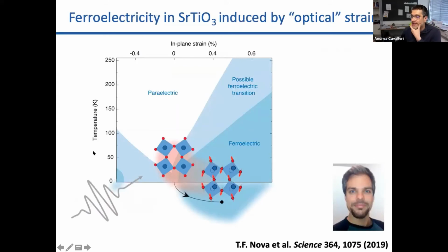This is work done by my student Tobianova, who took the famous failed ferroelectric strontium titanate, which is also known as a quantum paraelectric material, which never acquires ferroelectricity at any temperature, despite coming very close to it, at all thermally accessible states. We have shown that by using light and applying strain in this material, we could induce a ferroelectric state all the way up to room temperature. This was a metastable ferroelectric state in ways which cannot be done thermally, for example. So these are all examples of a seemingly uninteresting type of phononic coupling in which one could take a system like a failed ferroelectric, strontium titanate, and with this induce ferroelectricity.